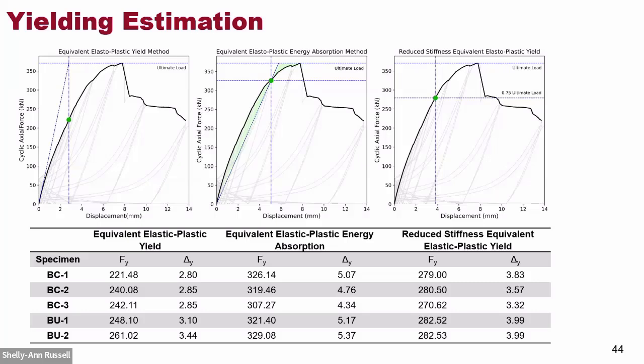And also the yielding strength of these elements is much lower than the theoretical calculations. And we observed that during the cyclic axial behavior, only the web of the section was effective, not the flanges. And when we take the area of the webs and multiply by the MPa that we observed during the material testing, we got almost the same numbers.